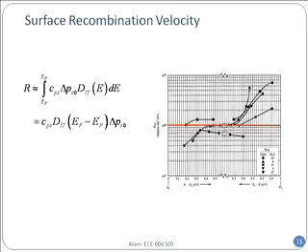And the excess carrier concentration delta P is there. Why isn't there any delta N or any N? Because this is donor doped. Lots of electrons, just a few holes here. So therefore, you only see delta P. It's not restricted by the availability of electrons, so you don't see any electrons here, right? And that whole term in the beginning is called a surface recombination velocity.